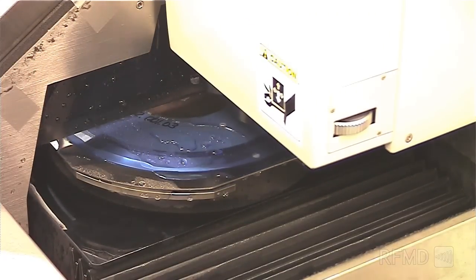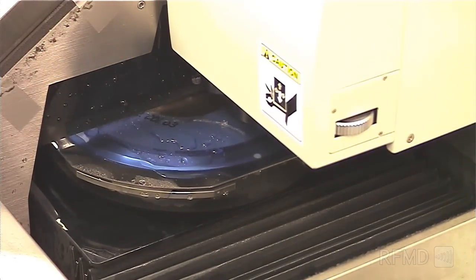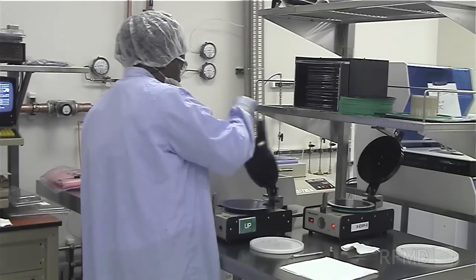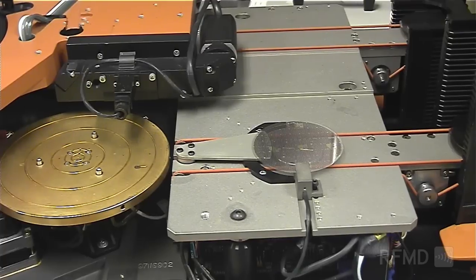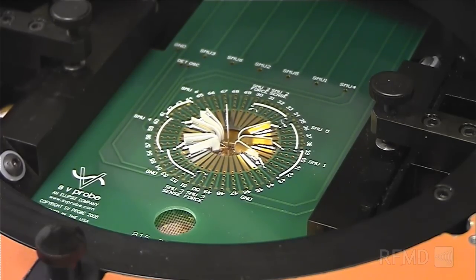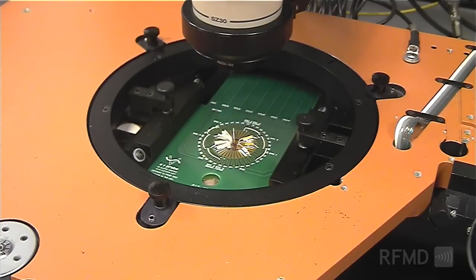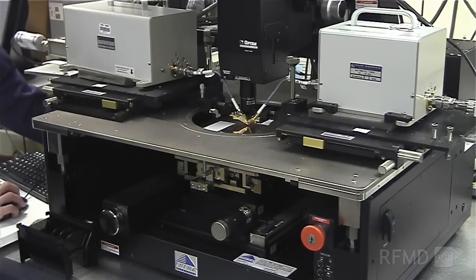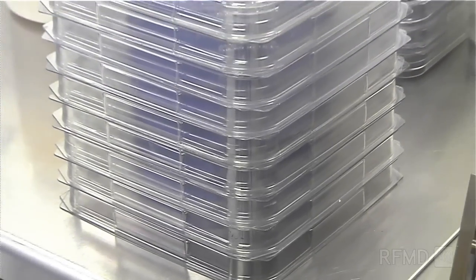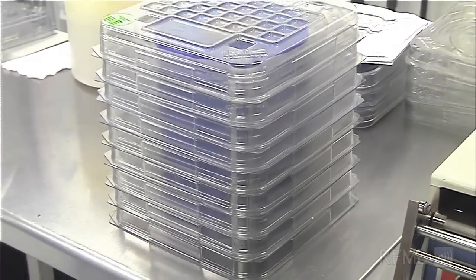In this facility, GaN on silicon carbide wafers are fabricated. After completion of the fabrication process, the wafers are thinned and diced. The wafers also go through 100% known good die testing as part of the process flow. Final testing reveals the wafer yield information needed for the GaN wafers that will be sent to the Broomfield facility for assembly into high-power packaging.